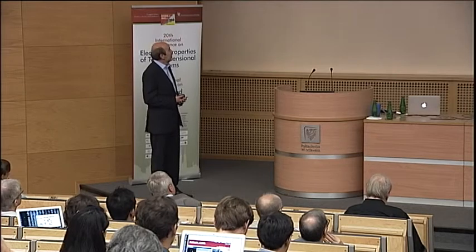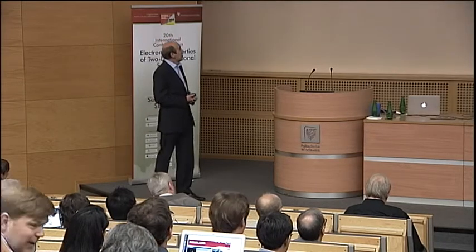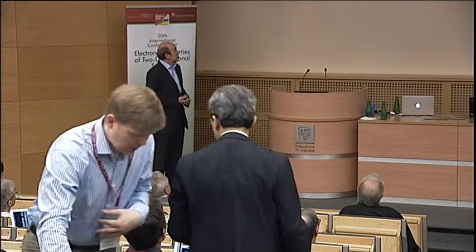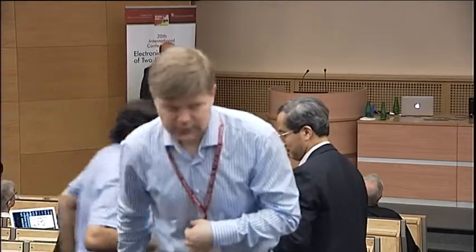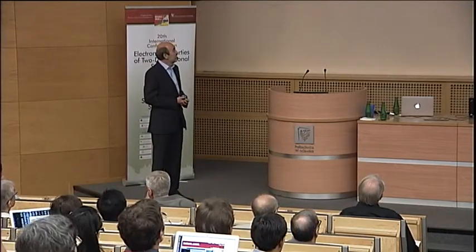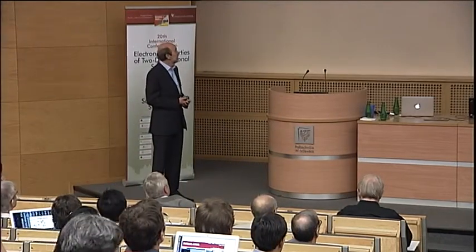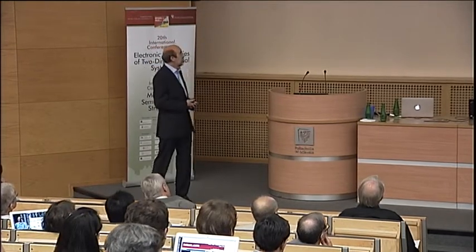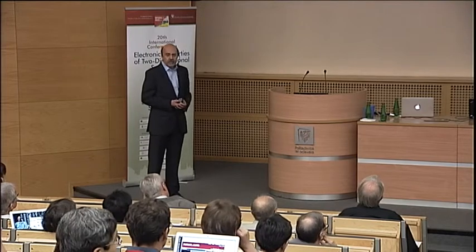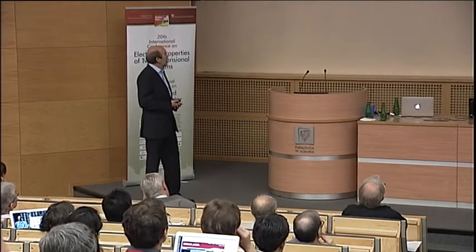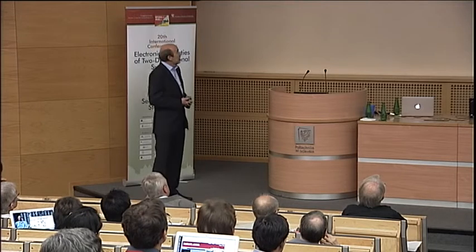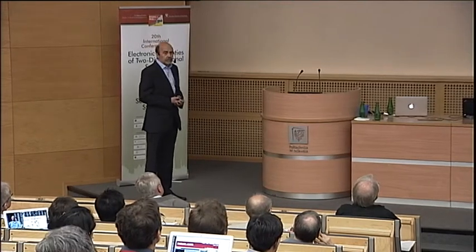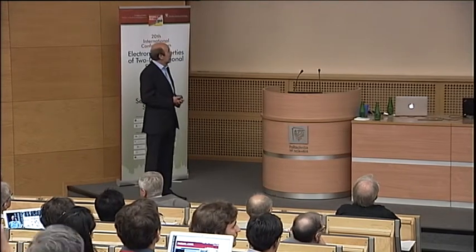And first, I'll show you results on the growth studies, which demonstrated that it is possible to improve mobility of two-dimensional electron gas in the structure, by setting the new world record in mobility of wide gap II-VI tellurides, and also the first observation of fractional quantum Hall effect in both non-magnetic and magnetic telluride nanostructures. And then I will proceed to show you some applications of those structures already published.